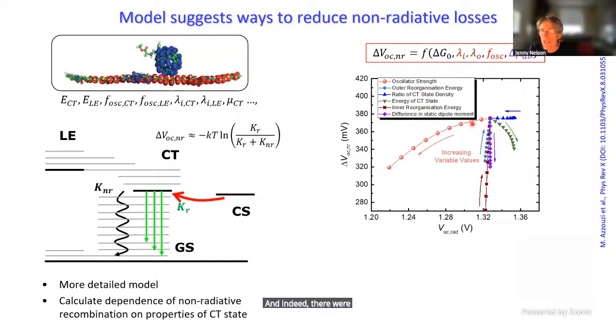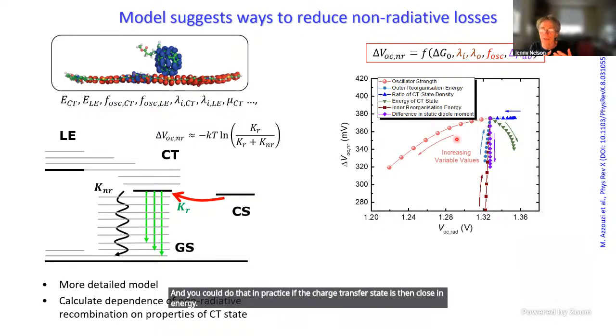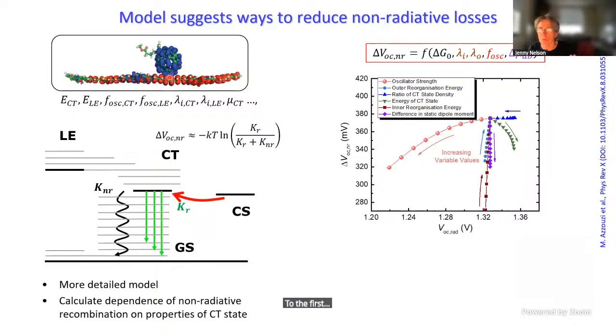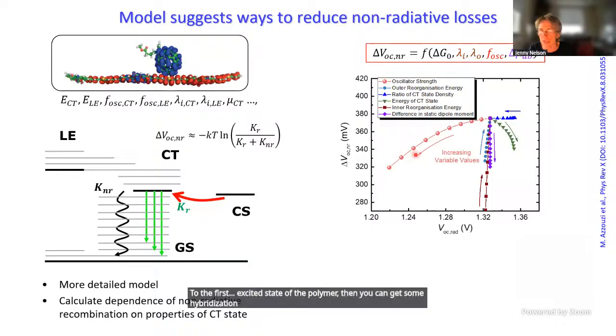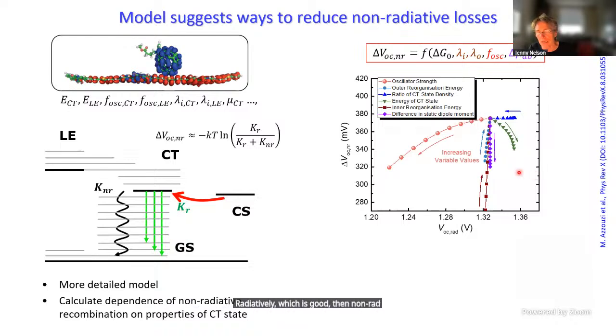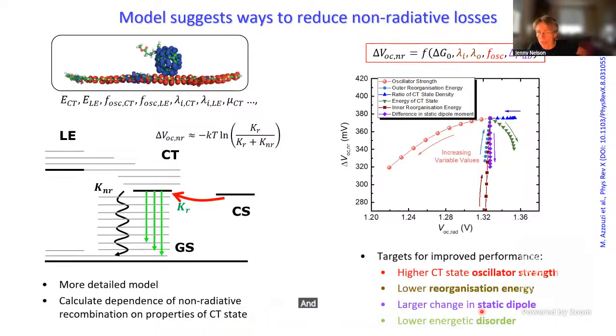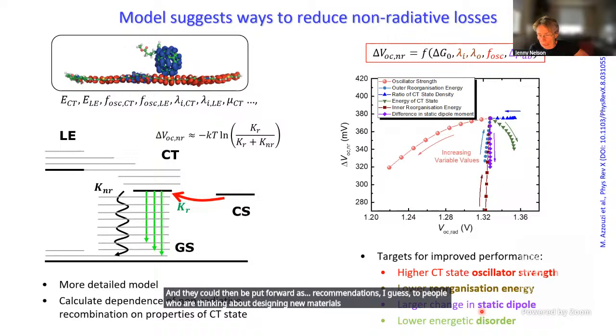And indeed, there were things that would help. One of them was to make our charge transfer state brighter. You could do that in practice if the charge transfer state is close in energy to the first excited state of the polymer, then you can get some hybridization and the charge transfer state becomes brighter, and then more energy would be lost radiatively, which is good, than non-radiatively, which is bad. Another thing would be to reduce the reorganization energy, or to change the amount of interface that you have. So there are some different ideas, and they could be put forward as recommendations to people who are thinking about designing new materials or new devices.